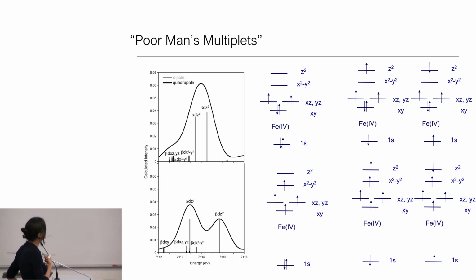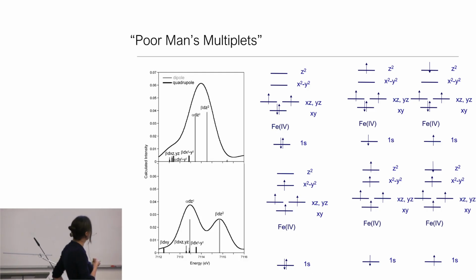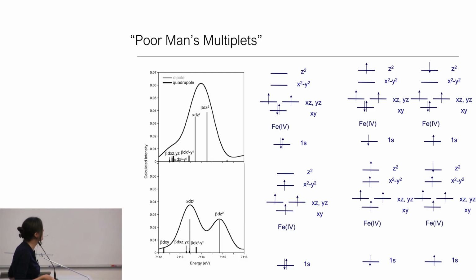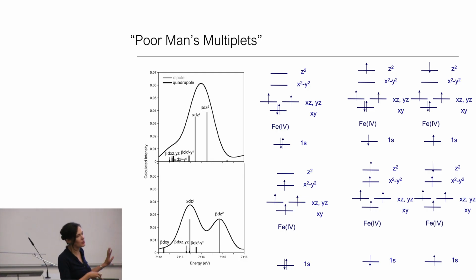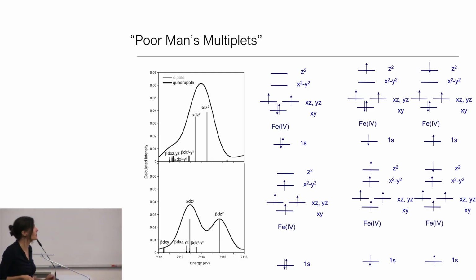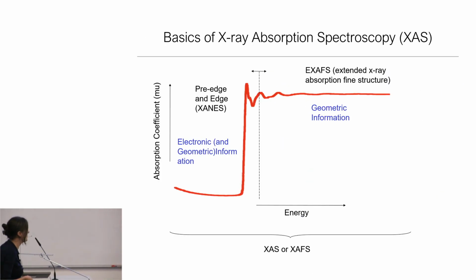And this was kind of a fun example. I realize I don't have the original reference in here, but this was actually a prediction that we made using ORCA together with Frank and John Barry before the first S=2 iron 4 oxo complex was synthesized. And then when we got the data, it really had this broadened pre-edge that's kind of become a signature for those complexes. And so that was kind of a fun example that the poor man's multiplets worked, and actually Frank didn't expect them to, I think. He always calls this criminally simple approach, but you know, it always has to just be tested against experiment.